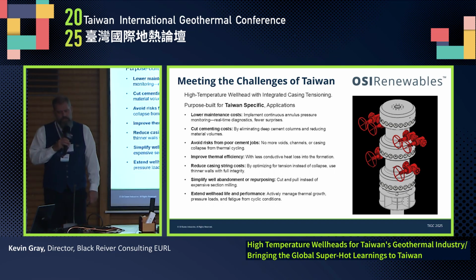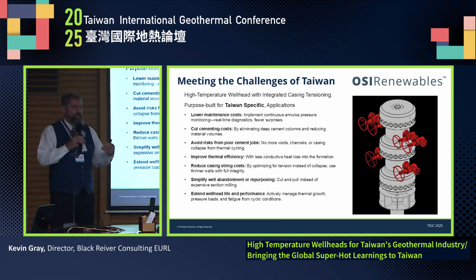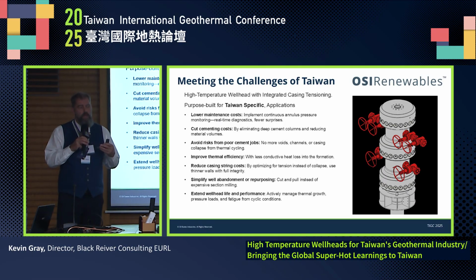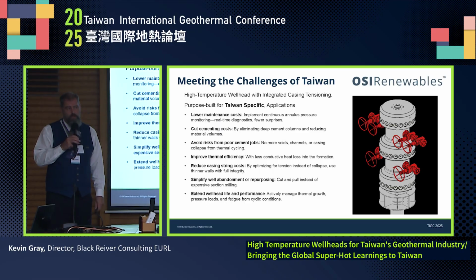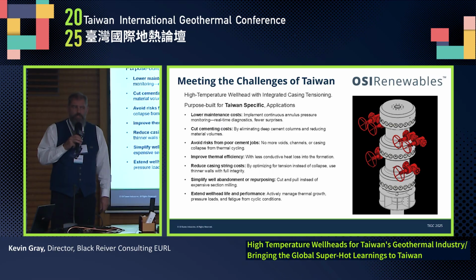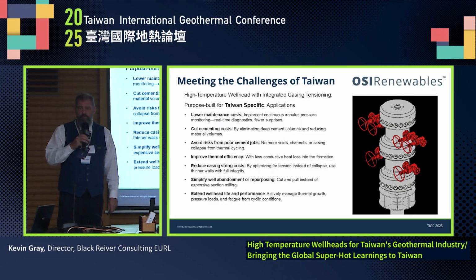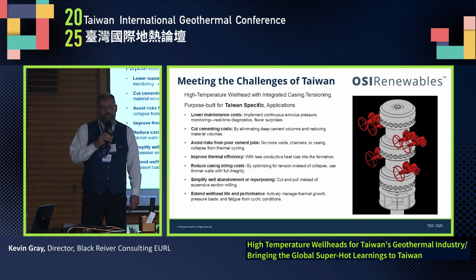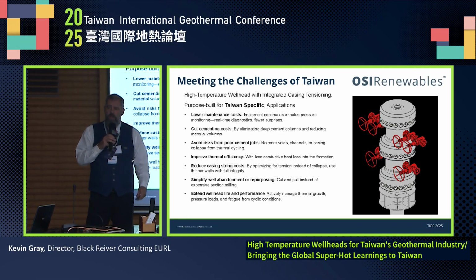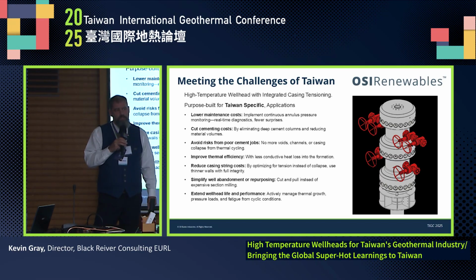One of the traditional ways of managing casing compression is by increasing the wall thickness of the casing. Your casing string compressive performance is a function of your wall thickness, and that's the primary way we deal with buckling resistance in most drilling and well construction. The problem with that in geothermal is that you're almost certainly going to be running very expensive corrosion resistant alloys. As you increase the wall thickness, your casing bill goes up quite considerably. So if we can keep the casing string as light as possible, as low a wall thickness as possible, we keep our casing costs down.